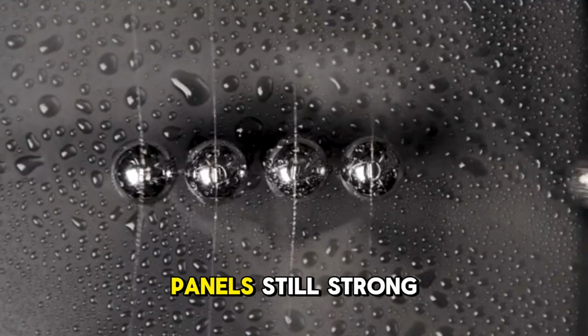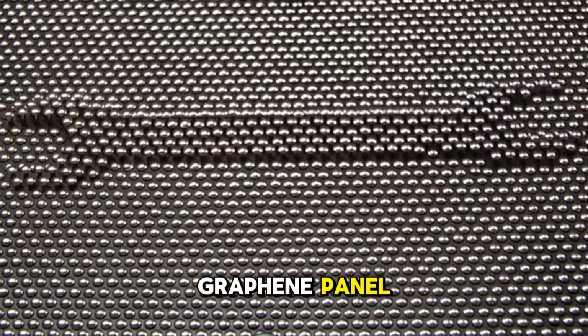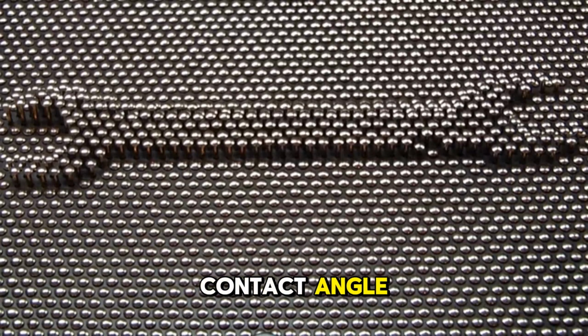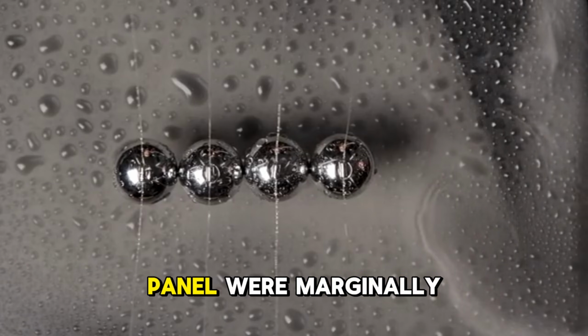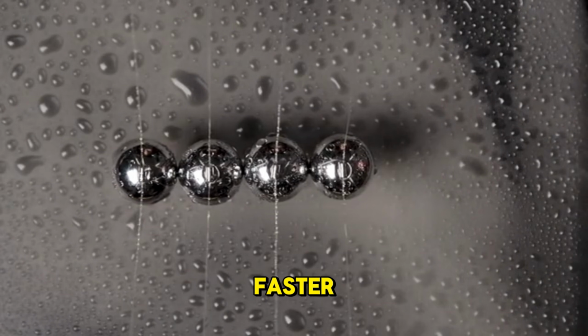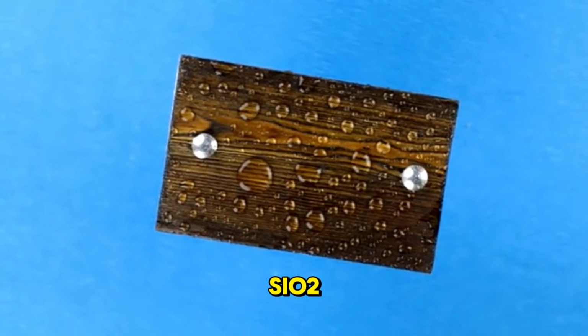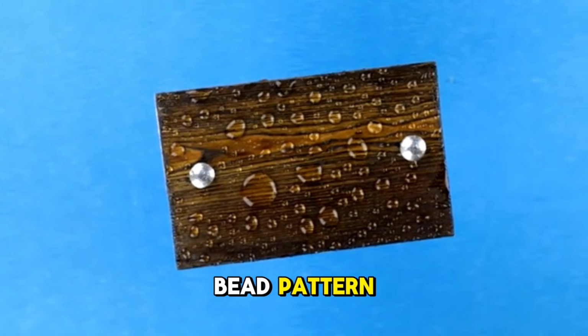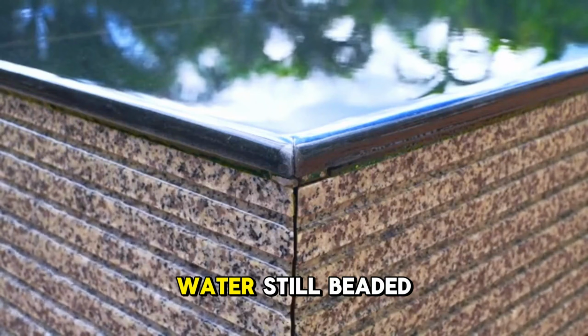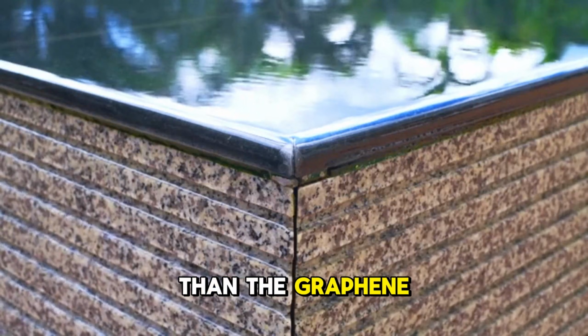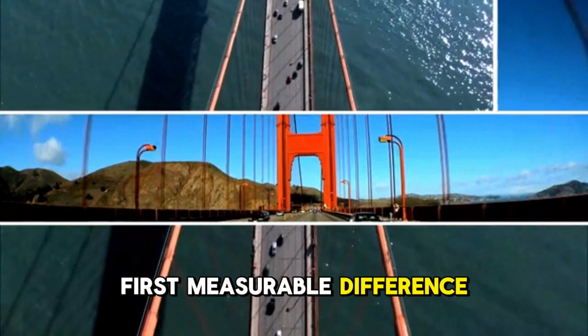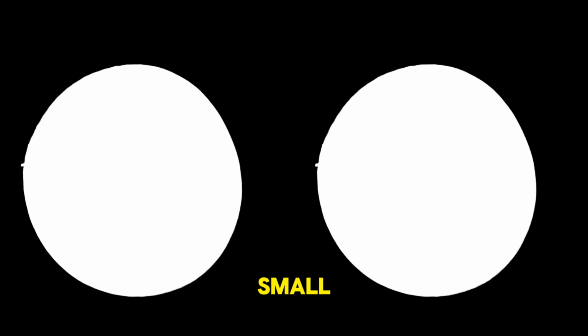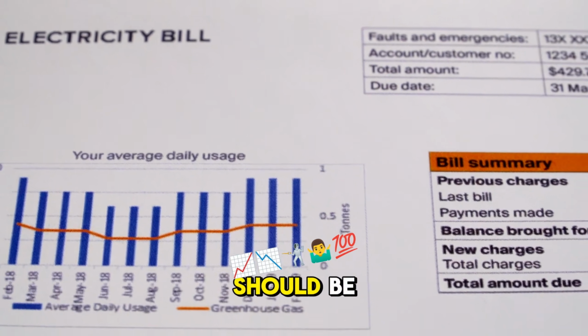Water beading, both panels still strong. Graphene panel, slight edge in water bead contact angle. The beads on the graphene panel were marginally rounder and rolled off faster. SiO2 panel, marginally flatter bead pattern. Water still beaded clearly, just slightly less aggressively than the graphene panel. First measurable difference at 3 months, and it was small, smaller than the price difference suggested it should be.